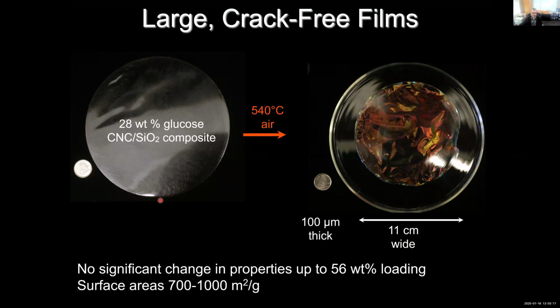Here is a photograph of that composite of cellulose nanocrystals and silica made using 28 weight percent glucose beside the dime. Again, we can make much larger films that are crack-free. When you calcine this in air, we can make large crack-free films of pure silica, and you can see that it's iridescent again.